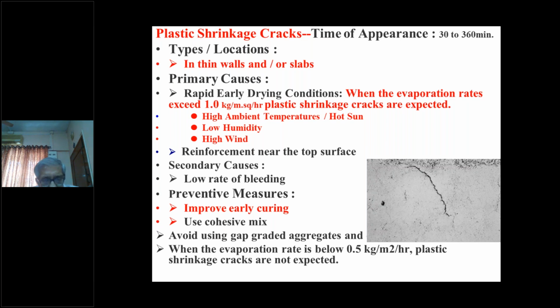When the evaporation rate is below 0.5 kg per square meter per hour, plastic shrinkage cracks are not expected. So you need not do curing. But generally you will always find this parameter exceeded. So one has to do curing not only immediately but also for the specified period of time, which is generally 7 days.